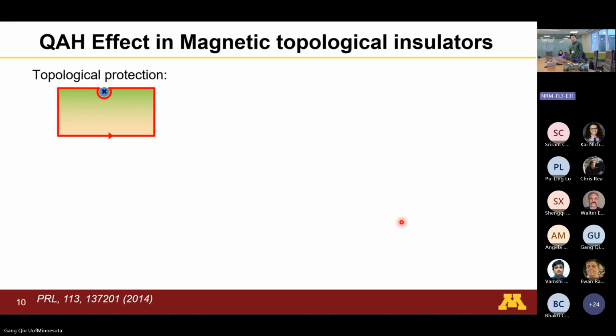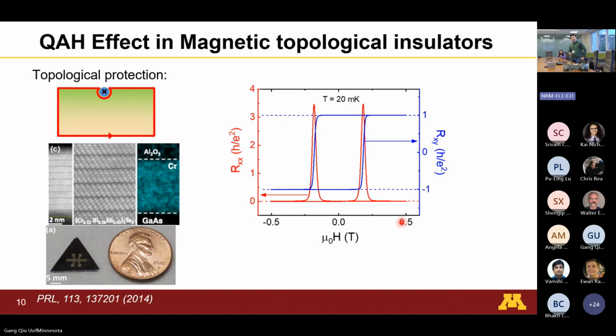Guided by these theoretical discoveries, around 2013 or 14, people finally realized this beautiful effect. We use molecular beam epitaxy to grow these thin films on gallium arsenide substrates. You can see this beautiful layer by layer structure of the chromium-doped bismuth antimony telluride samples. At that time, we could already do a centimeter-size wafer. This is a gallium arsenide 111 substrate. You can see we can achieve this macroscopic quantum anomalous Hall state.